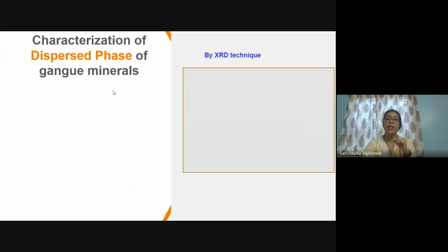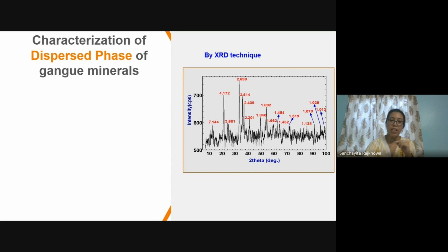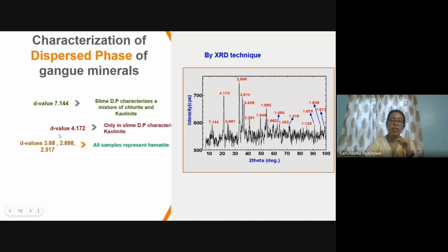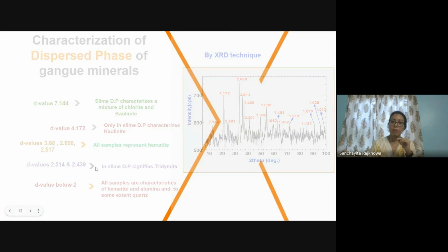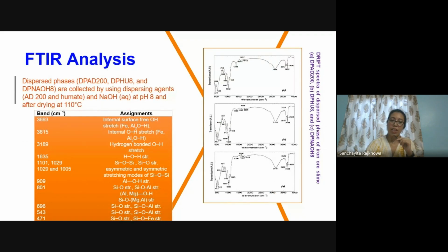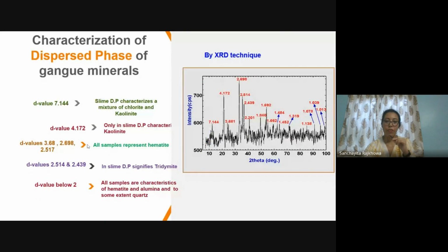And then we characterized the dispersed phase using XRD techniques, and these are different peaks which tell us about the mixture. For example, a D value of 7.144 signifies that there is a mixture of chlorite and kaolinite. Similarly, different D values give us different characterizations, and these are the contents that were present in the dispersed phase. Now, if we go for the FTIR study, that also gives us certain information regarding the dispersed phase, and these are well coordinated with the previous data.